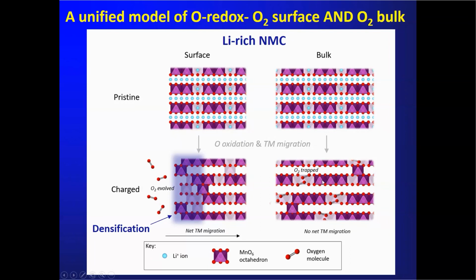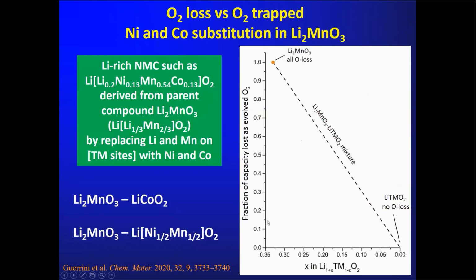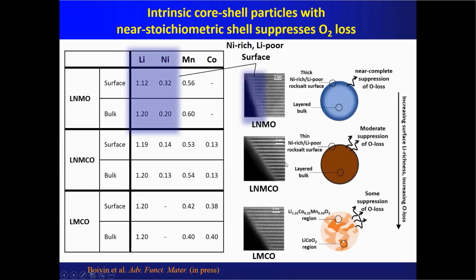In the bulk, so this stops, and the only other thing that can happen, the only game in town for the oxygen, molecular oxygen, is to get trapped in these vacancy clusters that I represented here. So I think my time is up, so I'm going to skip the next few slides and just go to the acknowledgements. I was going to tell you a little bit about how the substitution of various transition metals can have a huge effect on how much oxygen loss at the surface one encounters, and that's one of the reasons why the nickel-doped lithium manganese oxides have such low oxygen loss when Li2MnO3 is 100% oxygen loss. But in view of time, I won't go through that.